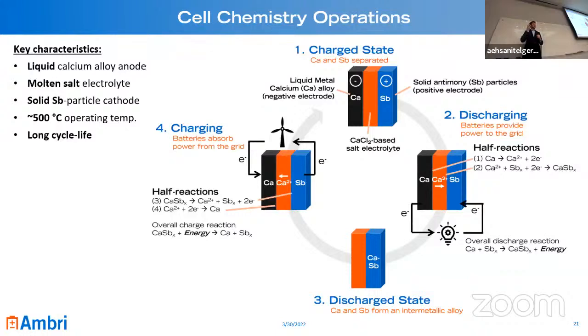Now, if you were just to take pure calcium and pure antimony and mix them together, they release a ton of energy. They can actually heat up to about 4,000 degrees Celsius just from the energy of that alloying reaction, which always boggles my mind because you're just putting metals together. But these metals in particular have a lot of energy stored in their potential bonds. But we don't want that to happen, obviously, in our battery. So we keep them separated by this layer of molten salt.